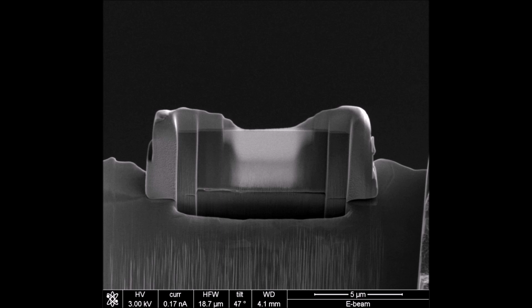And so the reason this is important is that I always have to keep in mind when I'm making the lamella that the area I care about, when I do the TEM, is basically right at the surface of the specimen. I don't really care about what's happening 2 or 3 microns down from the surface into the bulk. I only care about really right at the surface what's going on.